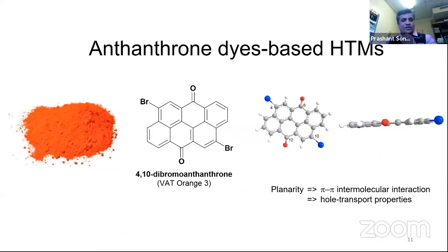So first we checked one of the dyes called anthanthrone. I mentioned it, vat orange. It is a very nice fused aromatic moiety. This dye we can get commercially very cheap, like $200 Australian per kg. And then using these two bromines, we can do some chemistry, and we also have this ketonic group here. We can do some functionalization, and look at that. It is very planar, with 6 benzene rings, a very flat aromatic core, and it has good pi-pi intermolecular interaction because of this flat nature. The benzene aromatic rings can stack very well, and it also has high hole transport property.